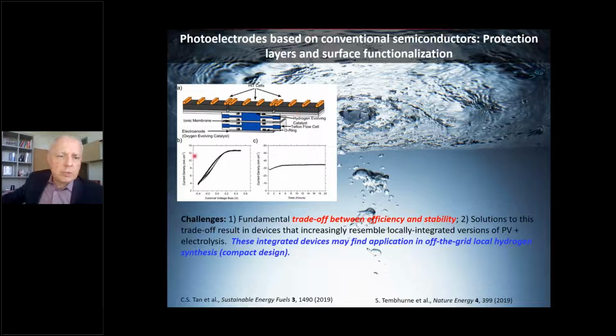With these kinds of approaches, it's possible to achieve very stable operation, in fact, for many hundreds of hours, and relatively high solar-to-hydrogen efficiencies greater than 13% in this case. But this fundamental trade-off between efficiency and stability is manifest here, in the sense that we have designed this kind of structure in such a way to avoid as many stability problems as possible.